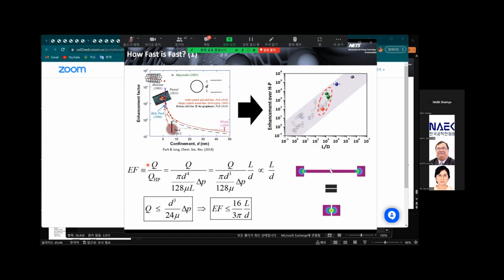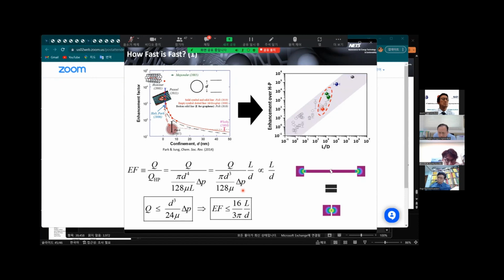If enhancement factor is linearly proportional to the aspect ratio of carbon nanotubes, it must come from the reference formalism to which we compare the water transport rate. By canceling out the aspect ratio L over D from both sides of this equation, we obtain a new scale for the transport rate of water flow through carbon nanotubes, the volume flow rate of water through carbon nanotubes. This volume flow rate is proportional to the cube of the channel diameter and independent of the channel length.